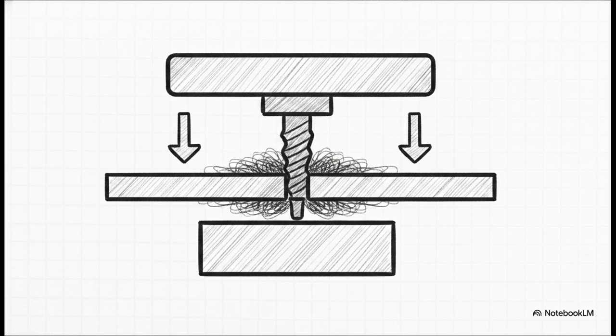Now, to do all that, the tool has a few essential components. First, you've got the shoulder, which rubs against the top surface. It generates most of the heat and acts kind of like a lid, keeping that squishy metal from escaping upward while simultaneously pushing downward. Then, sticking out below the shoulder is the pin or probe. Think of this as the actual stirrer. It dives deep into the seam, usually with threads or flutes to pull the material around. But here is the absolute catch. If that spinning pin goes too deep and hits the rigid steel backing anvil underneath, total disaster. The tool will either wear down instantly or just completely shatter.